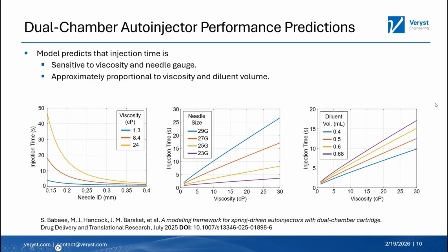So one of the advantages of having a model like this, once it's developed and validated, is that it can be used to probe sensitivities to design, operating, and material parameters. The model predicts that injection time is sensitive to needle gauge and drug solution viscosity. And it also predicts that injection time is roughly proportional to viscosity and the diluent volume.